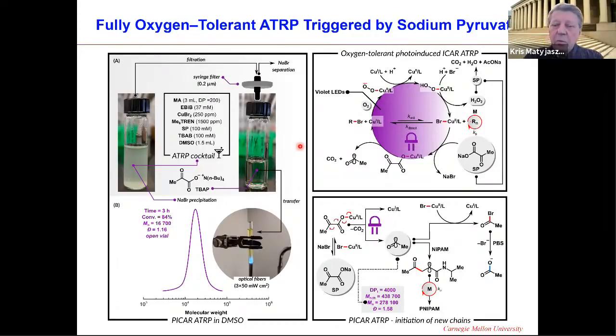So how this system works, it's a little bit complicated structure, but we have to realize that copper-1 can react with oxygen and form, like in this oxygen reduction process, eventually hydrogen peroxide. Then sodium pyruvate will convert hydrogen peroxide to CO2 and acetate anion, but also second part of the sodium pyruvate reaction is based on this exchange between bromide, formation of the light sensitive pyruvate copper-2 species, which then can be reduced to copper-1 by radiation and formation of these acetyl radicals.